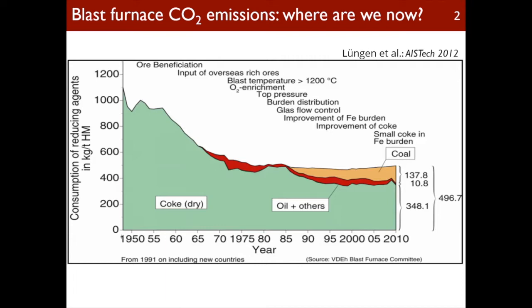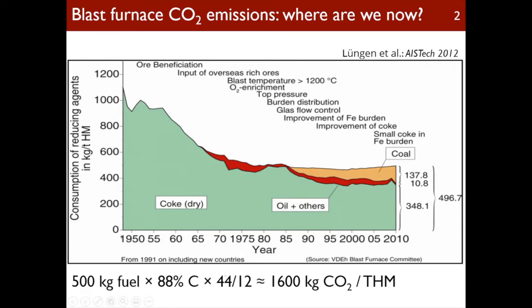So we're stuck at around 450, 500 kilograms of fuel, a combination of coal, coke, and natural gas. That means if we take an average carbon concentration in there of about 88%, that translates to 1.6 tons of CO2 per ton of hot metal. And if you add the other emissions from sinter production and coke production, you easily get to the 2 tons. And there's not a whole lot one can do about that if one sticks to a blast furnace, unless one starts recycling the top gas and sequestering the CO2 that way. And in any case, a blast furnace needs around 240 kilograms of coke to run. So we need to move to something else.